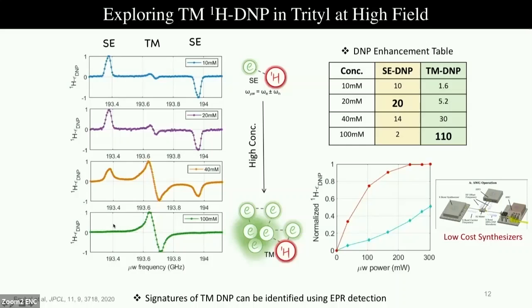The important thing about this finding is that the amount of microwave power that we require in order to achieve efficient thermal mixing DNP is much lower than what we would require for solid effect. Which means that we can do DNP with a low-cost microwave synthesizer. And this is very important in order to make DNP accessible to labs across the world. So this seems very exciting to us. And we can find the signatures of this thermal mixing DNP using EPR, something that I'll show you later in my presentation.